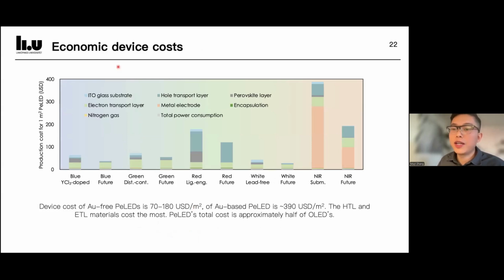Besides eco-friendliness, economic cost is, of course, another critical factor if we ever want to bring PeLEDs to market. So we estimated the production cost of different PeLEDs. We can see that for most gold-free PeLEDs, the total cost ranges between 70 and 180 USD per square meter. However, the cost for the gold-based near-infrared device jumps to almost 390 USD per square meter, more than double.